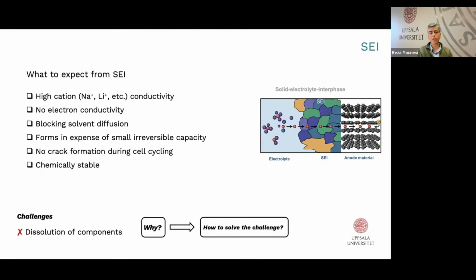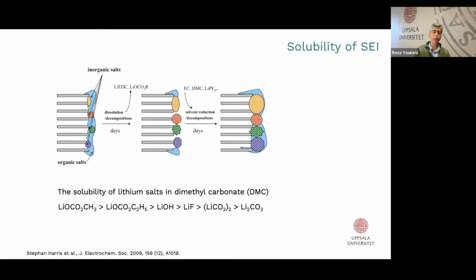That basically means we need to reform or form this species until there is no solubility of these species in the liquid electrolyte, so the electrolyte becomes saturated by all these species. We have been trying over the last few years to understand the dissolution of SEI, how this leads to aging specifically in sodium-ion batteries, and how we could address this issue.